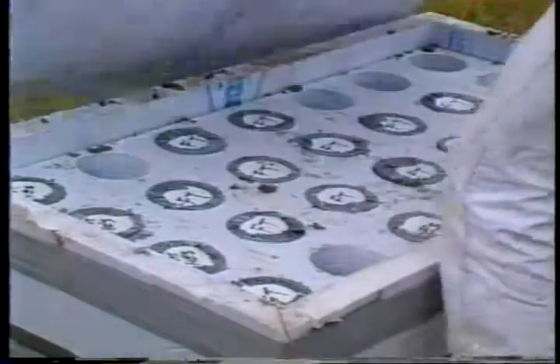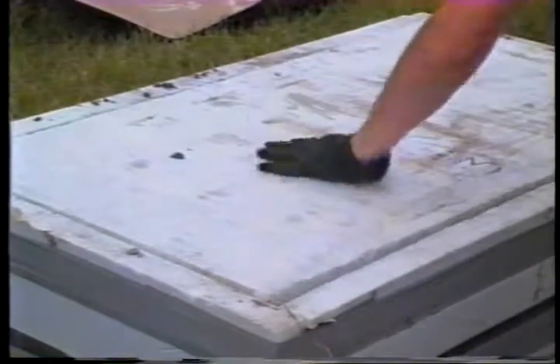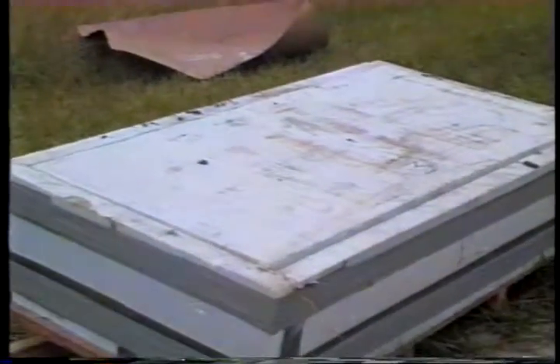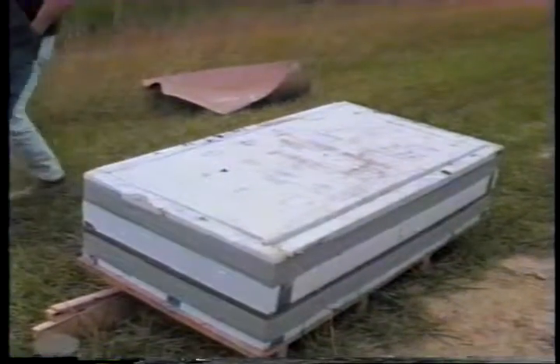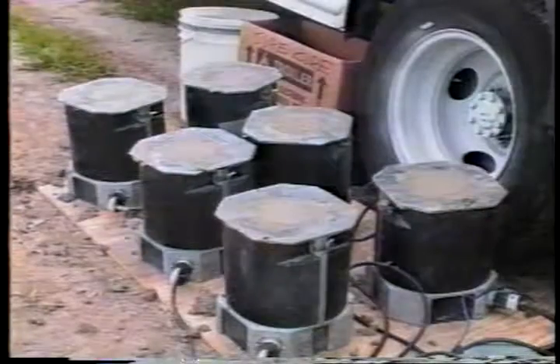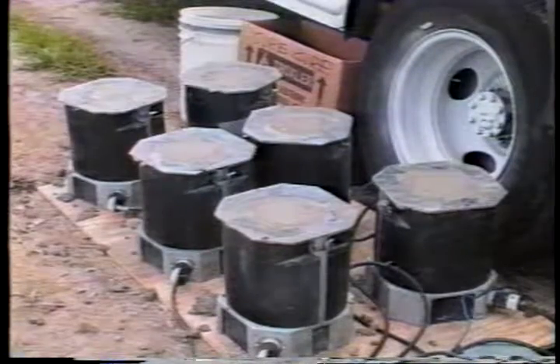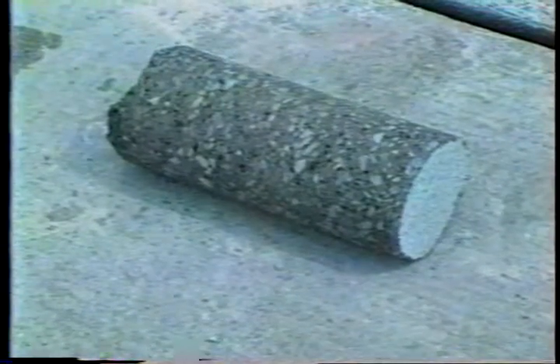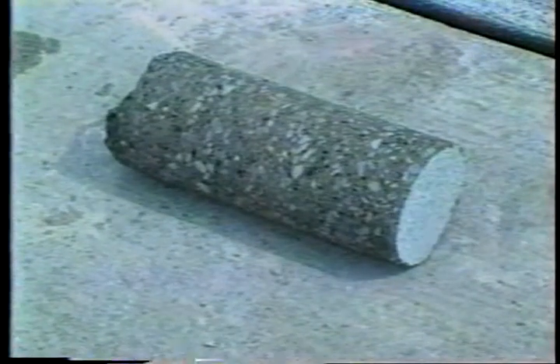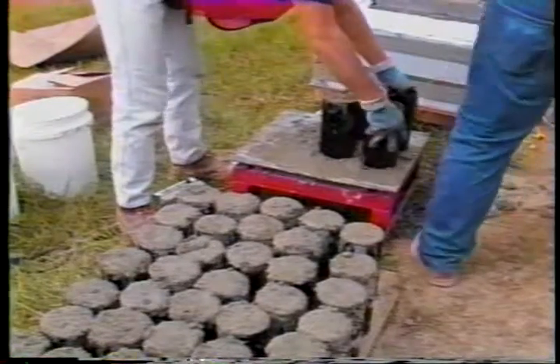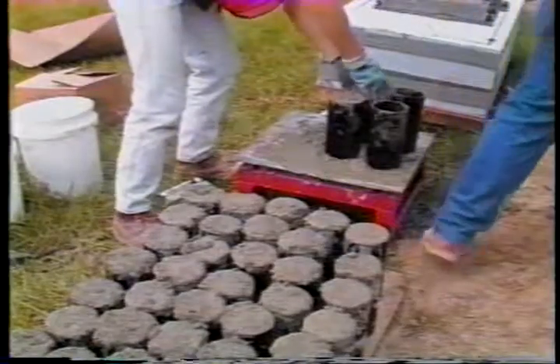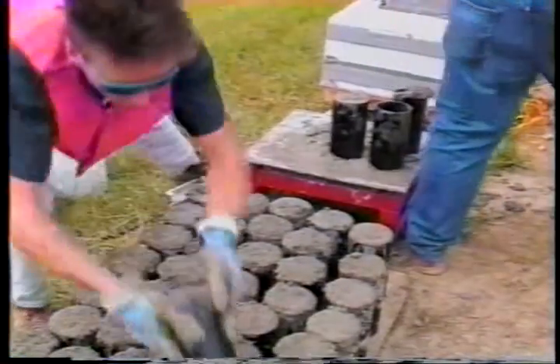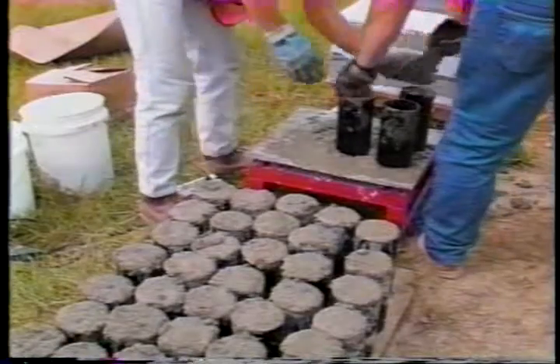It is well known that the in-place strength of concrete at early ages is much greater than that indicated by field cylinders. Several procedures can be used to estimate the in-place strength of concrete repairs. These include temperature-matched curing boxes, insulated cylinders, and cores. Sharp field testing results showed that concrete cylinders placed in an insulated box provide satisfactory indication of strength gain in the repair sections.